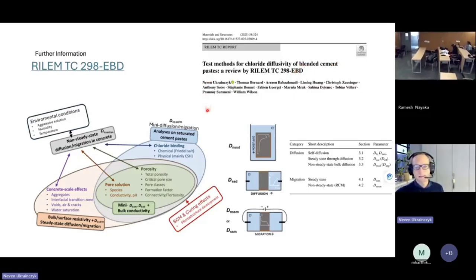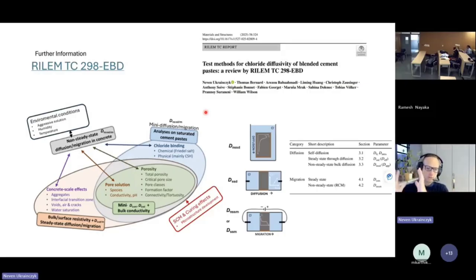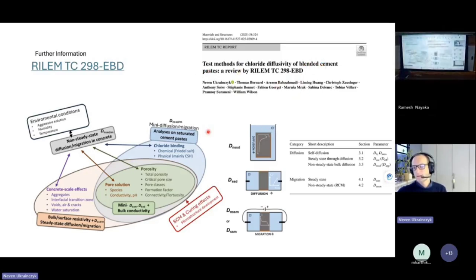So how to downscale, how to do fast measurements on paste, mortars, so that you don't do it only on concrete, but also concrete, and you can compare, and maybe speed up the measurements, so do the downscaling, because then you can also test the blended, the pozzolans, how they affect the diffusion coefficient. So we focused on blended cement pastes. Of course, we have to compare with mortars and concrete.